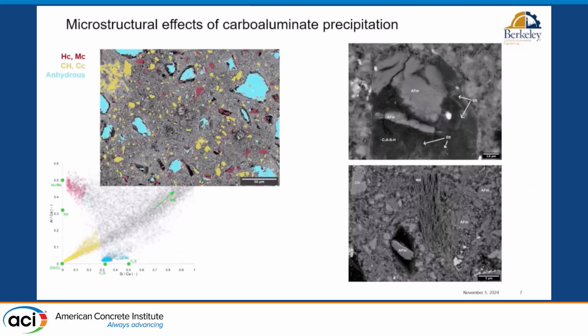What's cool of these phases, which are crystalline, by the way, and with this I want to mark on the point in the morning that you need an amorphous material in order to increase performance. No, what you need is to fill space and decrease porosity. AFM is a crystalline phase. We can actually see it by XRD, and this is how we quantify it. And from a microstructural point of view, these phases precipitate, in red here, in the large capillary pores that are left behind after clinker hydration. And if we look even closer, what we see is that these AFM crystals integrate between these CSH and other aluminate hydrates, creating something that is uniform and reduces porosity and provides mechanical performance consistently in our material.